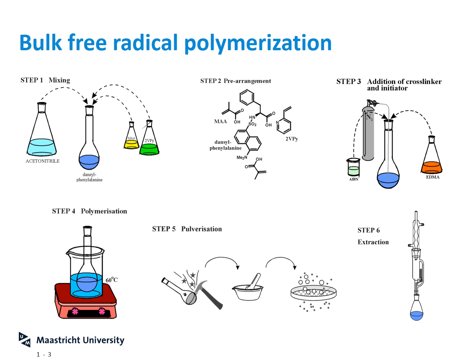This will be a group that will easily connect to other groups, and this will create a polymer chain that will be linked together by the crosslinker, and you will get in the end a monolith, basically a block of powder that you can crush and then sieve to select on size. And you will have all these small MIP particles with the target still in place. Now, obviously, you want the MIPs to rebind the target, so you need to get the target out. For this, we use an extraction procedure called Soxhlet, where you heat a solvent, and the solvent will condense down on the MIP and will flush the MIP in continuous fashion for multiple days. And when that is finished, you dry the MIP, and the MIP is good to go. The MIP can rebind its target.